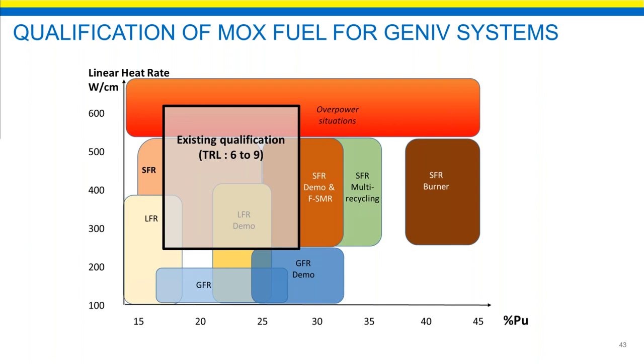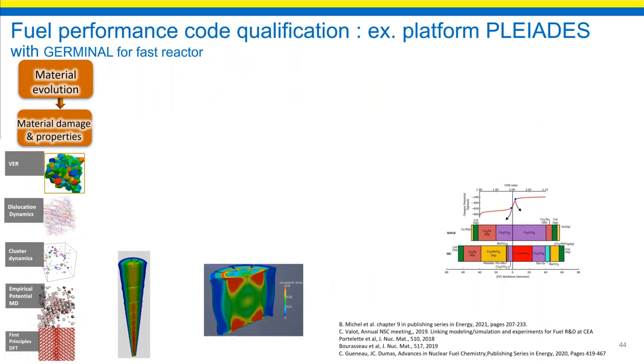And the whole core were tested until 13 atom percent with different safety tests. It was for the SFR. For the other systems that have different compositions or different conditions, the qualification level is lower. It's the case, for example, for the GFR and also for the LFR. Next slide, please. We have seen that the behavior of the MOX fuel is well known with phenomena identified as well as the coupling effect.